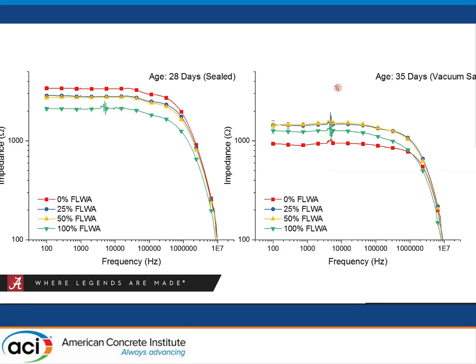And what's most striking about this is it suggests that if we go out to, let's say, a bridge deck that maybe has not seen a lot of rain, and we take our measurement, and then we are trying to compare that to a measurement we've taken in the lab where we had our specimens lime water saturated the entire time, we may get very different answers.